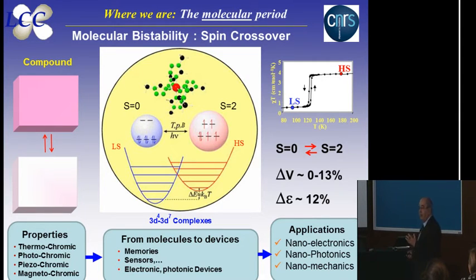So then that means that you have multifunctional materials, okay, where you can switch by temperature, pressure, magnetic field, and you have several properties you can use. You can use the optical properties, you can use the volume properties, the dielectric properties, and then when you have switching from one state to the other one, if the interaction between molecules is strong enough in the solid state, you can even have a hysteresis loop. Here, the χT as a function of temperature. When you go from the low spin to the high spin state, if the interaction between molecules is strong enough, you can even have a hysteresis loop here. Hysteresis loop means memory effect. So then at the molecular level, you can also have memory effect. Okay?